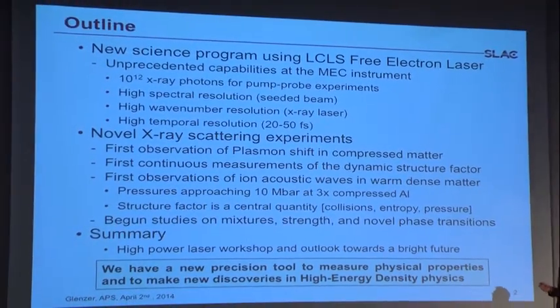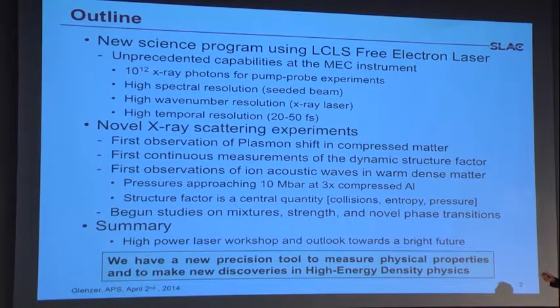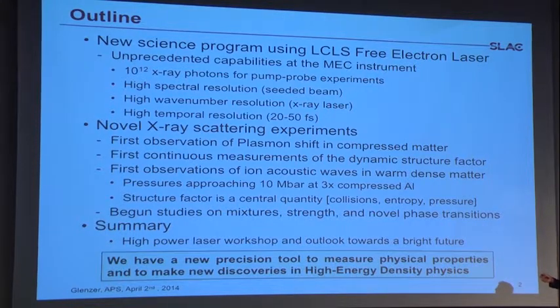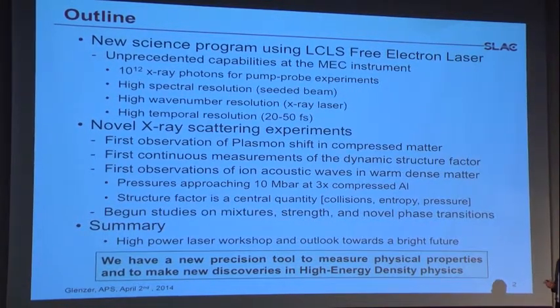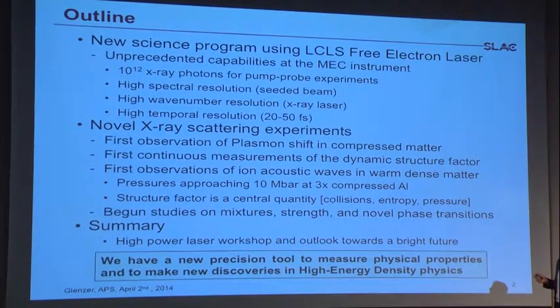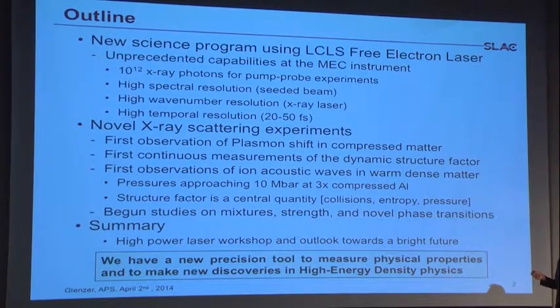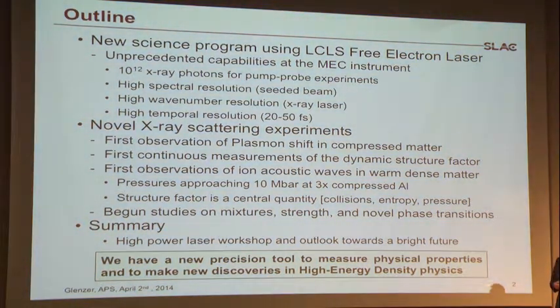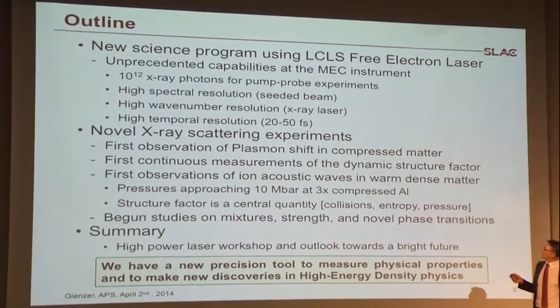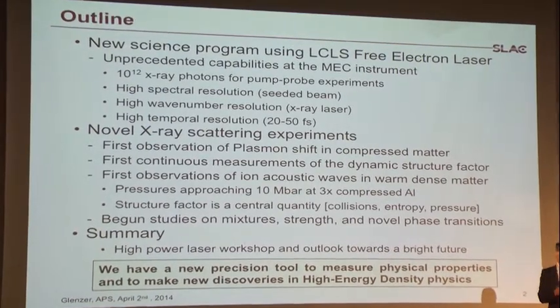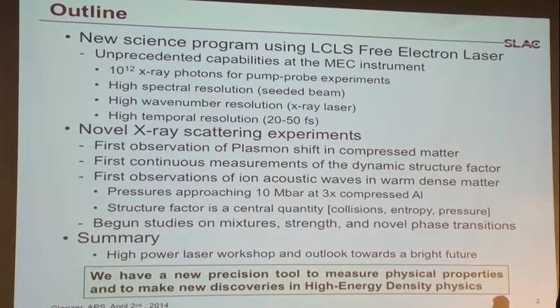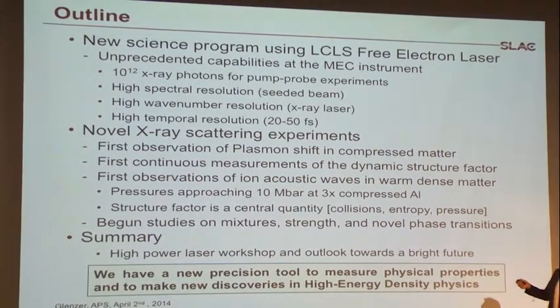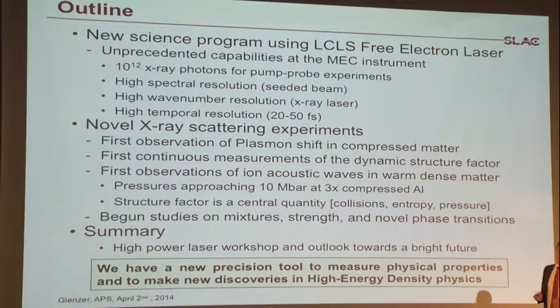That means we take advantage of the unprecedented X-ray flux, namely 10 to the 12 X-ray photons, to perform pump probe experiments. We take advantage of very high spectral resolution. We use a seeded X-ray beam. We take advantage of good wave number resolution that can be performed with an X-ray laser. And we have very high temporal resolution of order 20 to 50 femtoseconds. We just started this program, and we've already done a few firsts. So we have done some novel X-ray scattering experiments. In particular, we have seen plasmons for the first time at LCLS, and we've seen how the plasmons are shifting as we're compressing materials. We have performed the first continuous measurement of a dynamic structure factor at LCLS.